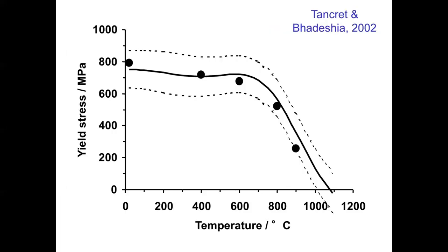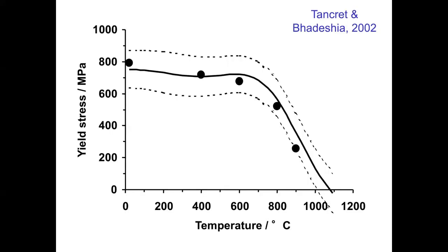And look, the data points that you see, those were not measured at the time that these predictions were made using our neural network model. So this curve was actually predicted, and these are our modeling uncertainties. And this is the strength as a function of temperature. Now, the reason why the strength persists to high temperatures is because in these precipitates, the mechanism of slip operates, which gets more and more difficult as you go to higher temperatures. Okay, so here, yield strength properly predicted.